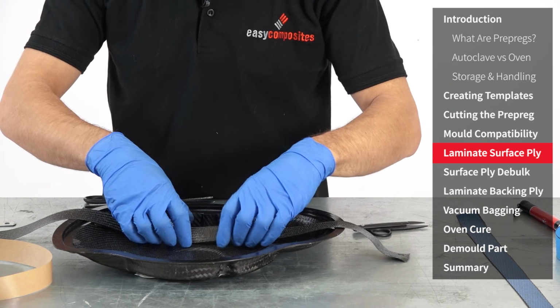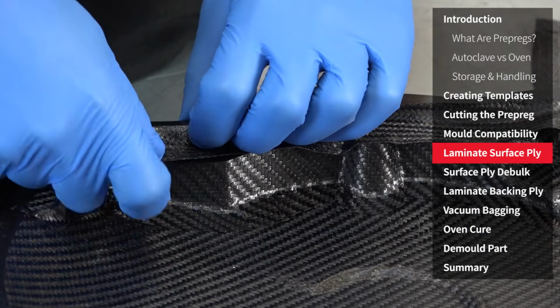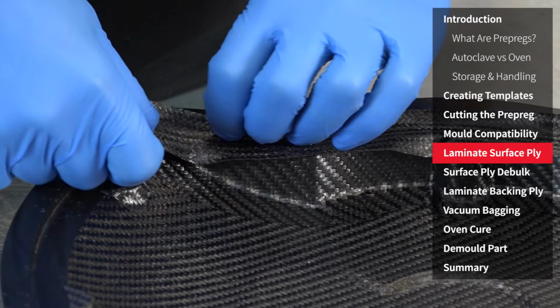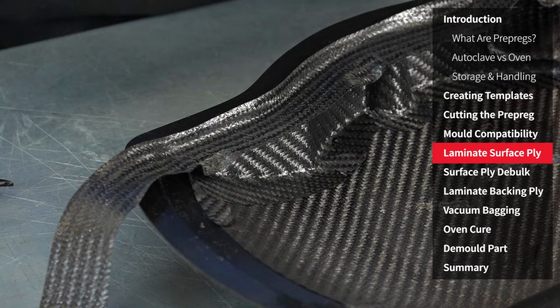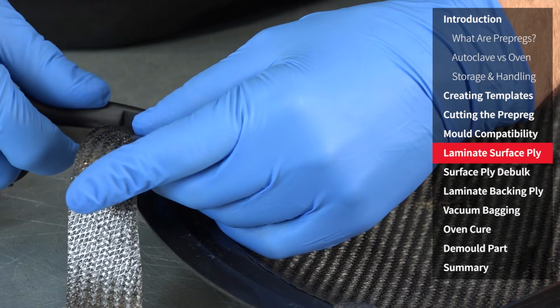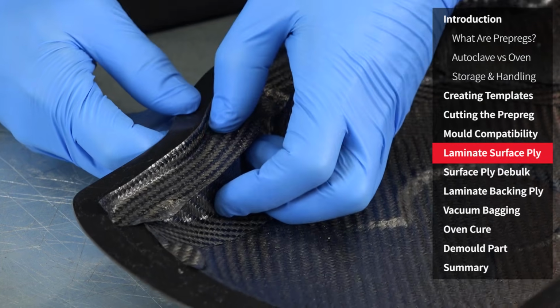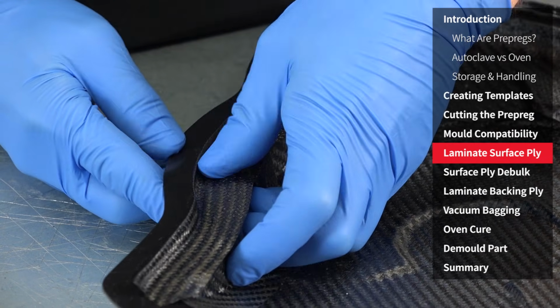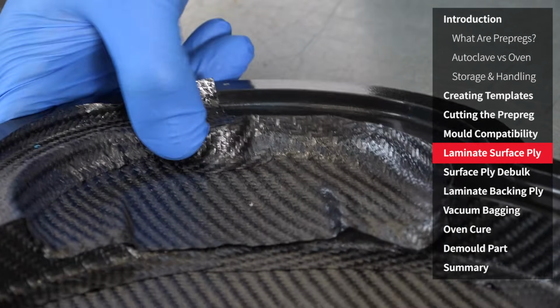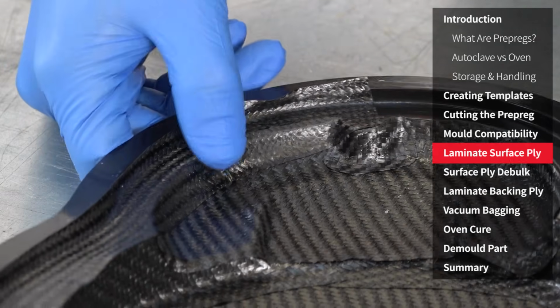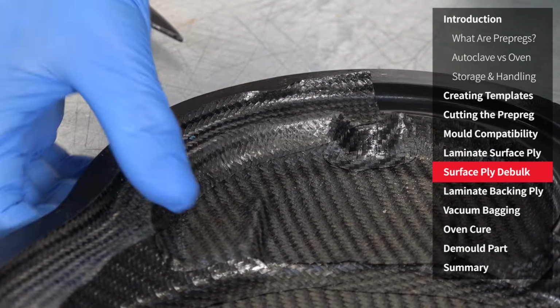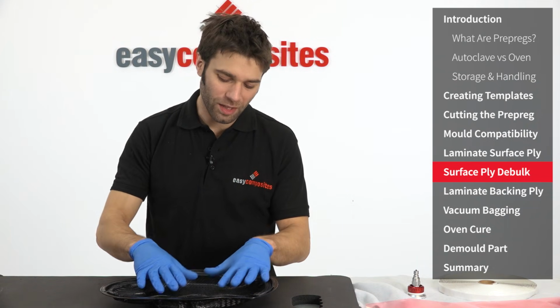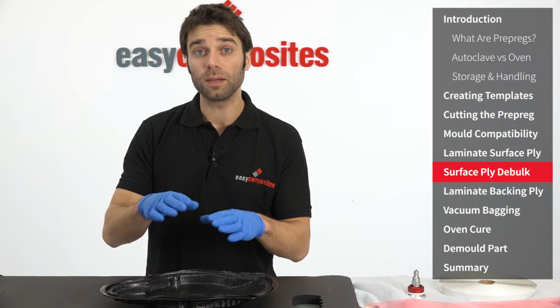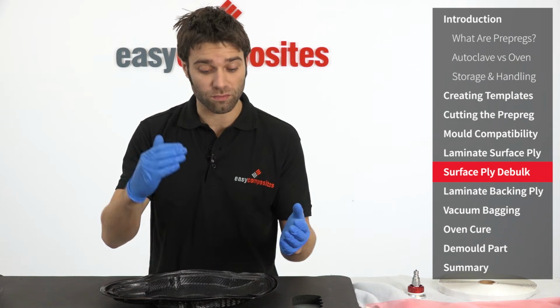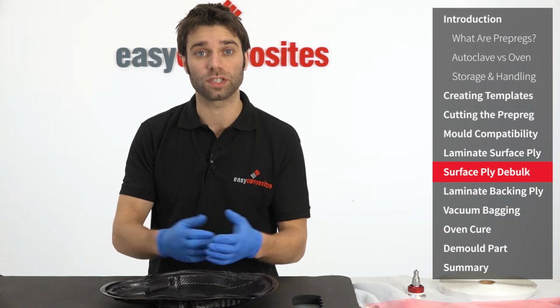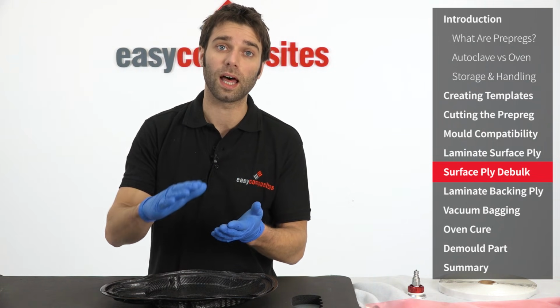If you can remember, these strips for the rim of the part were cut at 45 degrees. Cutting them at this angle allows them to follow curves very easily, meaning that they only need to be cut and joined on the sharper bends. This 45-degree cut also helps the material drape more easily into the mould, making the laminating quicker and reduces the likelihood of creases, so snipping is not normally needed. With the first ply down, I'm now going to do a debulk. Now, on a component like this, it probably isn't necessary, but a debulk can help to reduce pinholes and reduce bridging in larger or more complex structures, and certainly on laminates with multiple plies, they're a necessity.